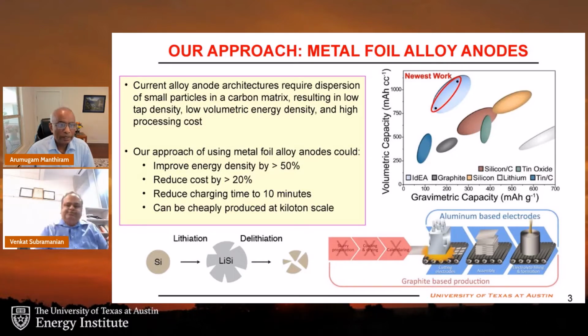And it also leads to high processing cost. Why do I talk about volumetric energy density? For all portable applications like laptops, cell phones or electric vehicles, volumetric energy density is the most important because there is not much space to keep the battery. So our approach is not to use that kind of dispersing the active material in a carbon matrix, where you have to make slurry, coat the slurry, dry it, all those steps. Those steps involved with graphite and the other ways of using alloy anodes can be eliminated with our new approach.